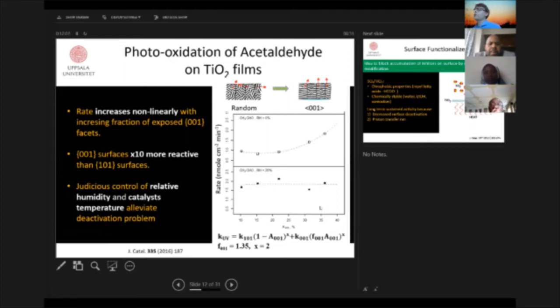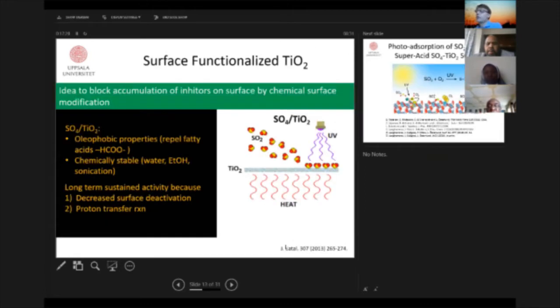So we have come up with a scheme how to prepare films on a large scale potentially, where you have a sustained higher activity, avoiding this deactivation mechanism. So this comes to the end of the first part here of how to make materials with sustained activity. Still, they are not super active in terms of efficiency, and still they are prone to some deactivation, as you also noted in some of the slides.